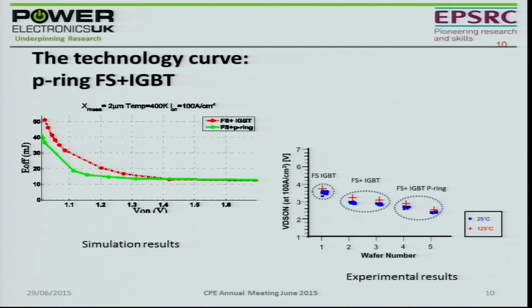If you look at the switching performance of these devices, on the left there, you can see that, again, there's a comparison between the field stop, this generation of devices, and the one with the P-ring. You can see that the closer to this corner you get, the better the performance of the device. You can see there's a dramatic increase in the switching performance of about 20%, which is very significant for these type of devices. So that piece of work has been going on, and it's producing real devices now, and they are being looked at, being exploited commercially.